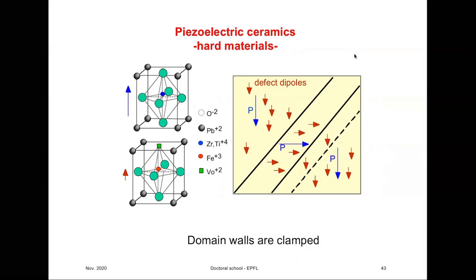So the oxygen vacancies are very mobile at those temperatures. Polarization sets in, and that polarization forces oxygen vacancies all to align in such a way. So if this is direction of polarization in surrounding lattice, the defects, which we have only one iron atom instead of titanium on 100 titanium atoms. So it's rather diluted. There is enough energy for this oxygen vacancy to align in a cell in which we have defect with those cells which don't have defects. So we will have alignment of defect dipoles and dipoles from the polarization, ferroelectric polarization. So these are defect dipoles, and this is the polarization in the cell.